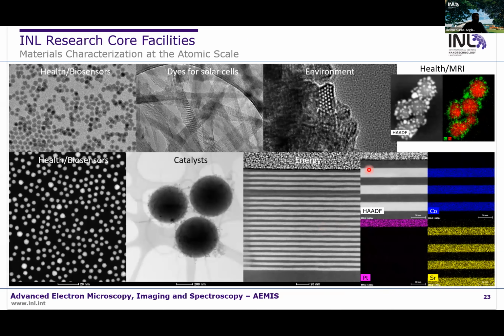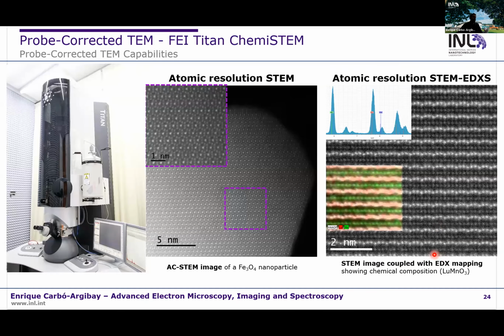In comparison with this, we have the images that we can get in a TEM. As I showed before, also we can combine it with chemical analysis. And another advantage of the TEM is that if we have a corrected TEM, it means that we have an accessory in the microscope that is a corrector. We can get relatively easy atomic resolution.